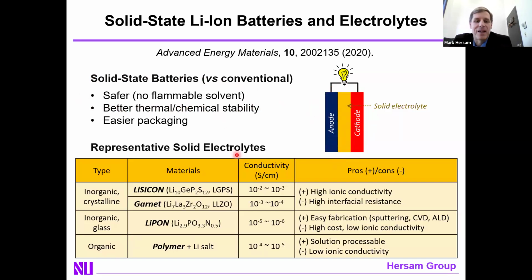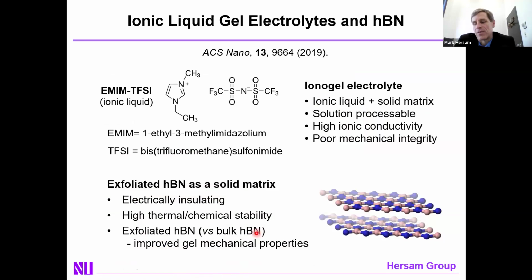People have been trying to realize solid-state batteries for several years now, and some of the candidate materials are shown here. I'm not going to walk you through them in any detail other than to highlight that they all have some issue, like high interfacial resistance, poor ionic conductivity, difficult to process, high cost, and so on. And as a result, none of these has really made it, or at least are not widely deployed yet in a commercial setting. And as a result, it seems like there is opportunity to develop new types of solid-state electrolytes.